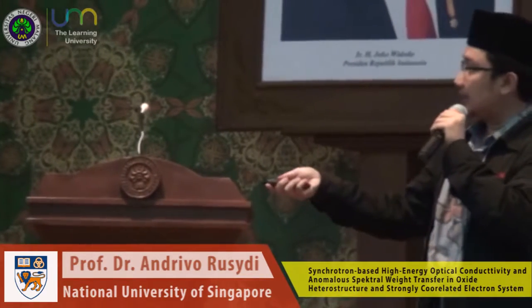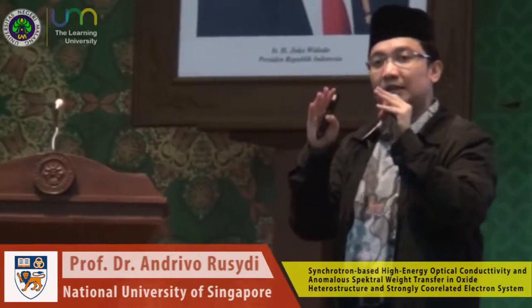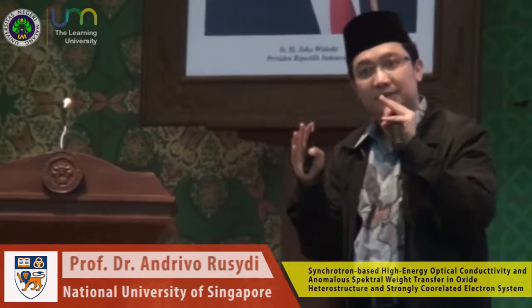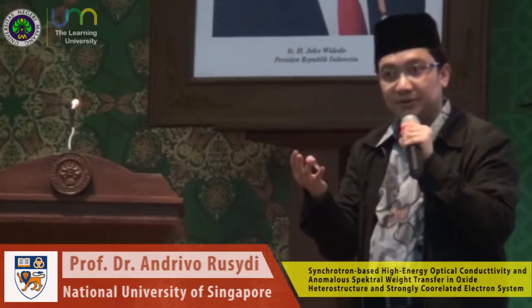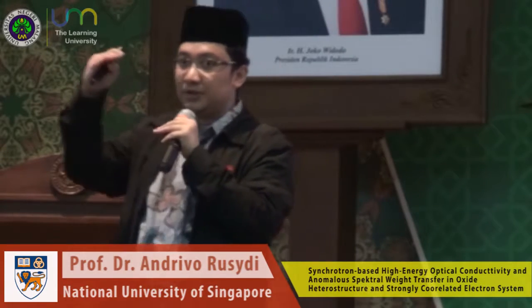Again, this is only atom by atom. You don't put everything there at once, but put one atom on top of another. Then they can measure the sheet conductivity, which is the inverse of resistivity. If the sheet conductivity is zero, that means insulator. There's no charge carrier over there. If the sheet conductivity increases, that means towards a metal. So take a look at this.